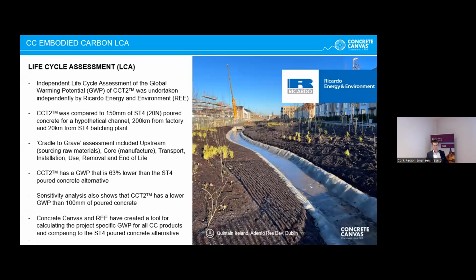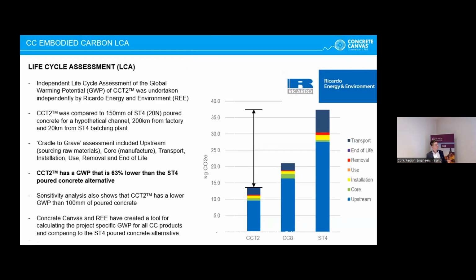And again, in terms of the life cycle assessment of the material, Ricardo Energy in their report ran this LCA, and basically, for people who aren't familiar, it does a cradle to grave assessment. It includes everything from sourcing your raw materials to manufacture, transportation, installation, and end of life. When they ran the report, they found that the global warming potential of a GCCM product type 2 is 63% lower than a 150 millimeter of poured concrete. You can see on the table on the right-hand side all the different points they've taken into consideration. So this is a really useful tool for a lot of the designers looking to work with GCCMs.